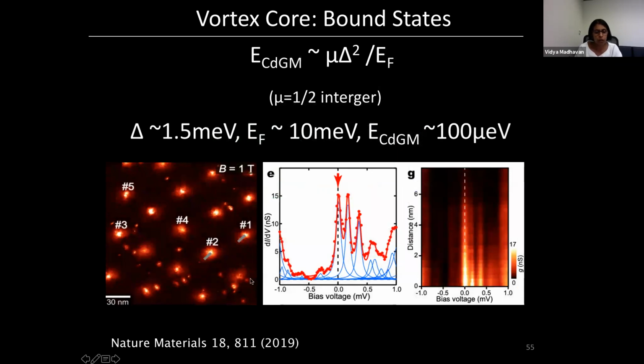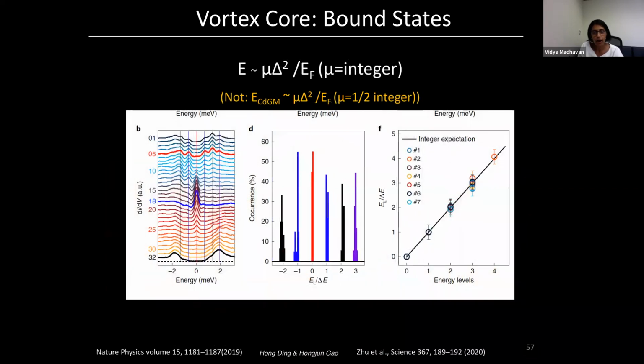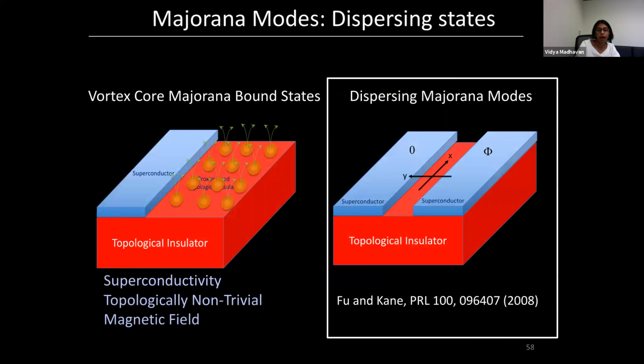So, this is work by Hanaguri in Japan, and they've shown that these zero bias states are in fact at zero to very high precision and very far from the 100 microvolts that the ordinary Caroli-de Gennes state should be. There are also other measurements that I don't want to get into, this is showing you that the spacing between these special vortex core states is actually integer instead of half integer. So if you take all of the supporting evidence, there's a lot of compelling evidence to indicate that these zero bias peaks that you see in these vortex cores are indeed what we've been searching for all along, which is Majorana fermions.